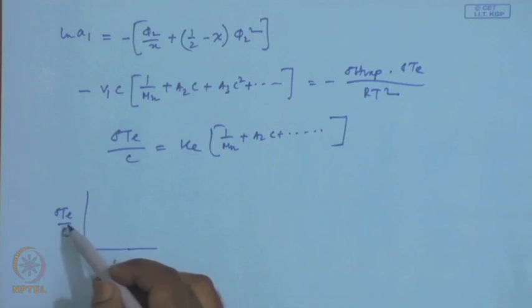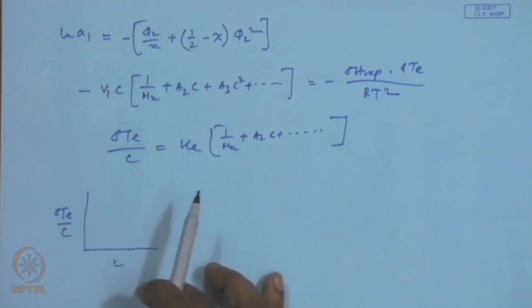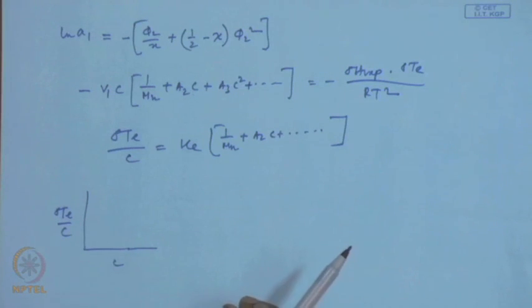In practice, we actually do not reach equilibrium, because some of the heat of condensation of the droplets gets dissipated on the thermistor and the solvent stream. So, what we reach is not a true equilibrium, it is a steady state. So, we need to calibrate the experiment with known molecular weight polymer solutions to determine the number average molecular weight for the unknown samples. This is not an absolute method; we need calibration.